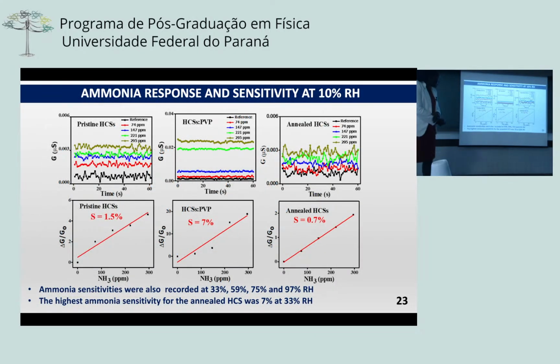So we controlled the relative humidity of the environment, and then we tried to detect ammonia, and you can see here for the pristine, it does very, very poorly. And also the annealed also does poorly. However, the polymer gives us a 7% sensitivity. So the same was done for all the other relative humidities to see whether we can detect ammonia in a humid environment.